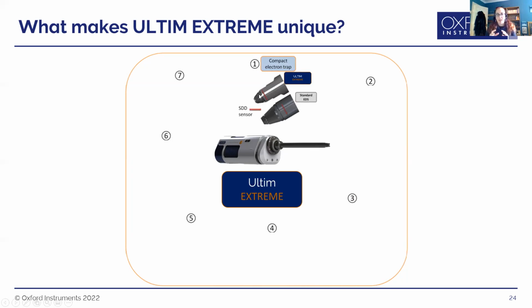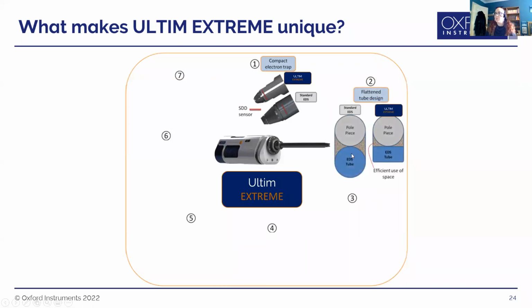The electron trap is there for when you've got backscattered electrons coming out, to make sure they don't hit your detector, because you want to be detecting the X-rays, not the backscattered electrons. We also changed the shape. If you've got two circular things, they can't get as close together. So the snout of the Ultim Extreme detector is more like this, and it means we can get closer to the pole piece. We don't have a window, and that window absorbs some of the light energy X-rays emitted from your sample. So by removing the window, we can detect all the X-rays that are coming in.